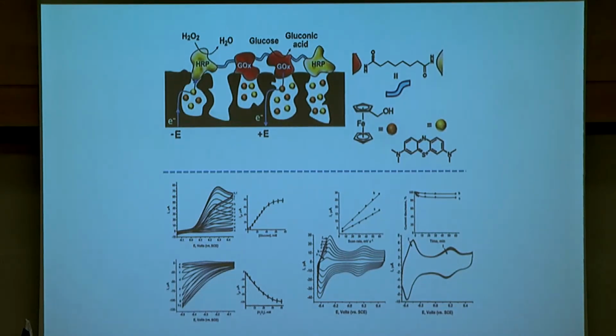porous carbon nanoparticles and using the pores of the nanoparticles as a container of redox active components. For example, we immobilized into these pores of the carbon nanoparticles either ferrocene units or methylene blue units, and we loaded the pores with enzymes, glucose oxidase or horseradish peroxidase. And once we loaded these pores, we got entities that are totally integrated, contain a high content of these enzymes and the relay units, and they are extremely well electrically contacted.